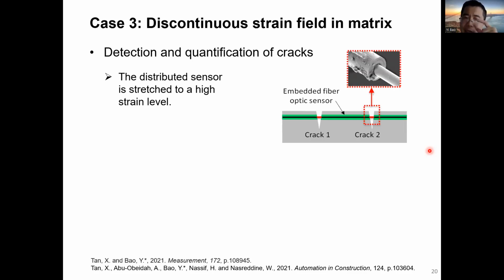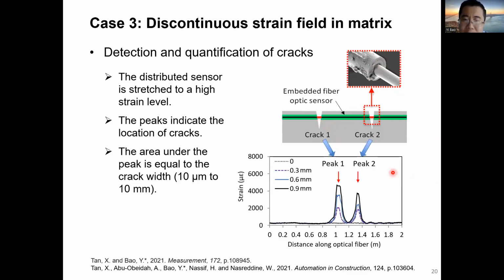And here you can see a SEM picture showing the debonding at the interface between the glass fiber and polymer coating. So because of this debonding behavior, the abrupt, very sudden deformation at the crack opening will be averaged over a debonding length, which is longer. So therefore, we could use fiber optic sensor to actually detect and locate cracks. And we can use a single sensor to map a lot of cracks.